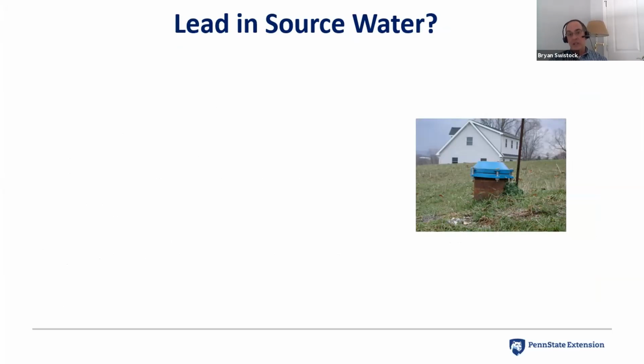This has been challenging in the past because for a long time we had problems with lead corrosion even down in the well, and we still have a little bit of that, but there was a time when some of the submersible pumps had lead impurities in the actual pumps themselves. And so if you put that pump down into a well with corrosive water, it would slowly dissolve away the casing of that pump and would produce lead actually down in the well.